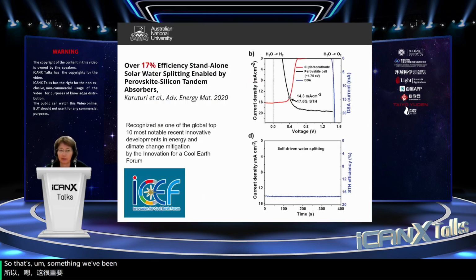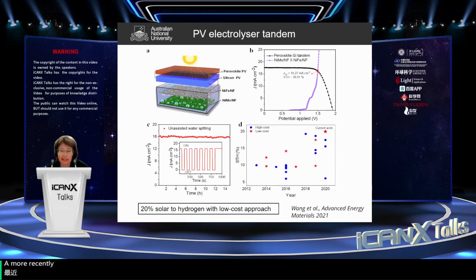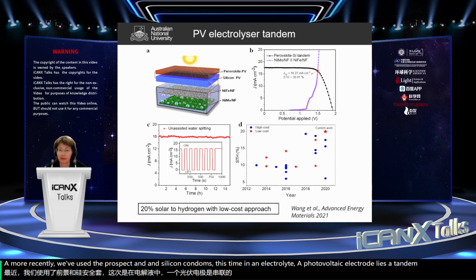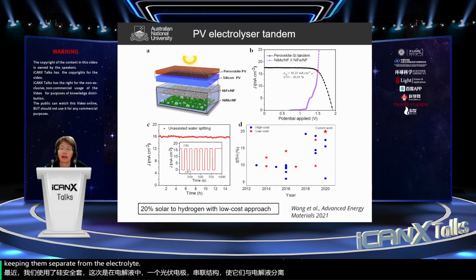So that's something we've been working on. We achieved over 17% standalone water splitting in 2020. So using a silicon photocathode connected to an electrolyte in that case, and adding a perovskite cell to increase the voltage. More recently, we've used the perovskite and silicon tandems, this time in a photovoltaic electrolyzer tandem configuration, so keeping them separate from the electrolyte. And in this case, we also added low-cost catalysts. So these are nickel iron, nickel molybdenum catalysts, so avoiding any noble metals in order to reduce the cost of the whole system. And overall, we were able to get 20% solar to hydrogen using a low-cost approach. And that's very important, again, for reducing the cost of the whole system.